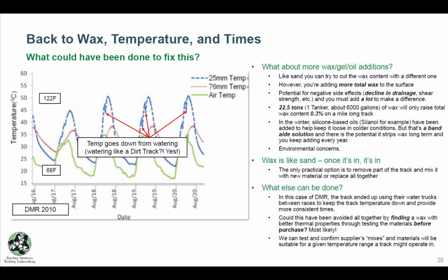identified to characterize these materials, is that we can actually test and confirm suppliers. If a supplier is going to come out to you and say, I have this material, and we're going to add it to the track, we can actually show and see whether this material is right for you to add to the track, and whether it is actually going to help address the problem, or potentially not do anything at all. So we are able to look at the thermal properties of these materials, we can identify them, and we can help make data-driven decisions on whether or not you would like to move forward with a wax or not.